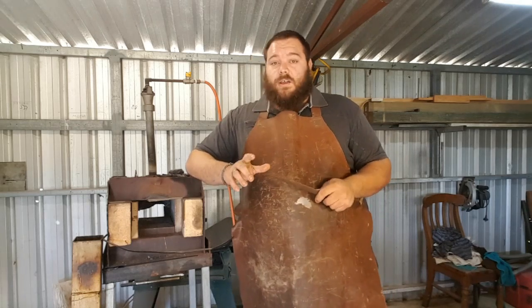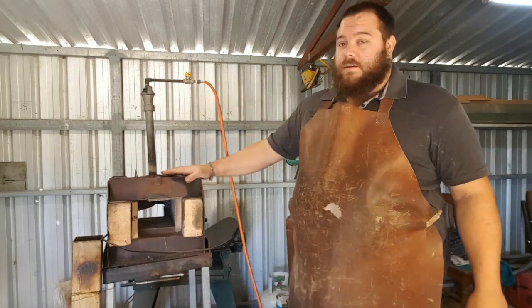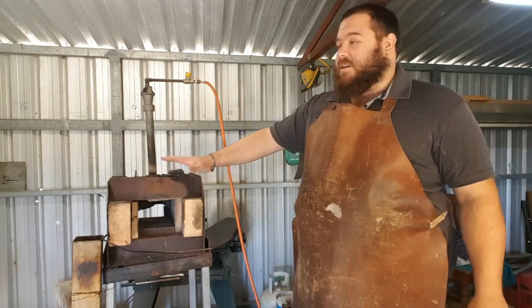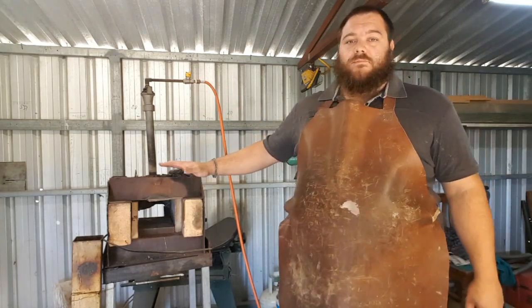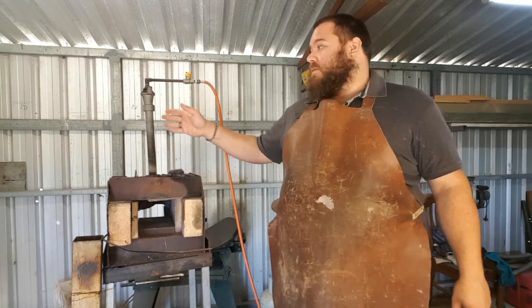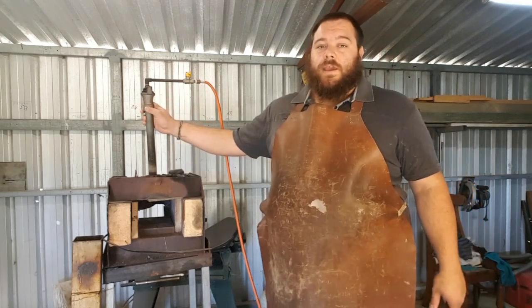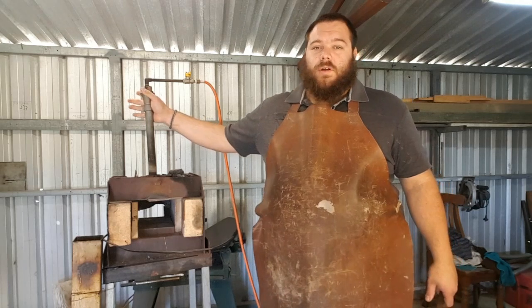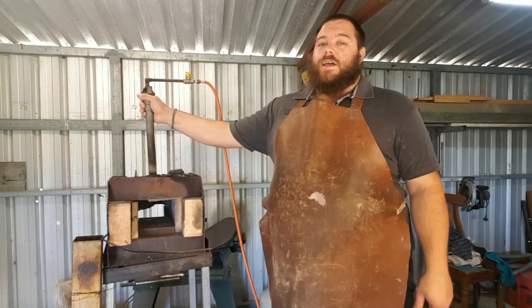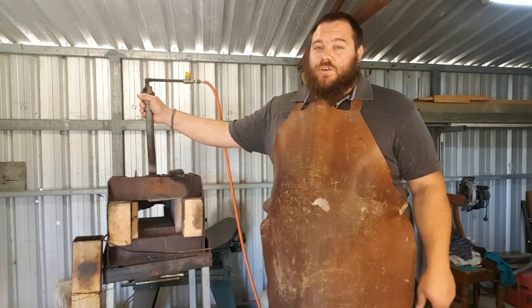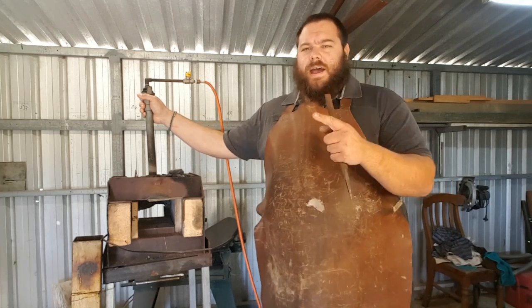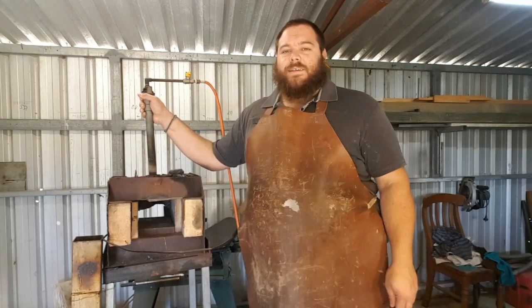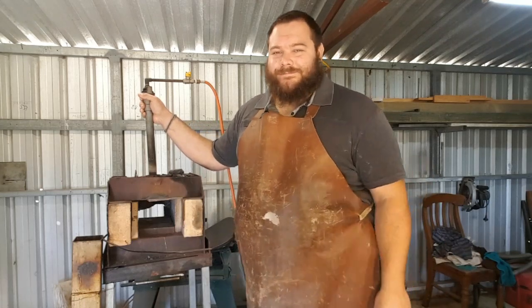So to start off with, I'm going to take you through running my gas forge. And this is a forge that is fairly indicative of most gas forges, and the reason I'm doing this is because this requires tuning. If you are running a charcoal forge to heat treat, you don't need to do this step. So you can skip ahead, and I will try and add a time link somewhere around here that will show you the next stage of the process.